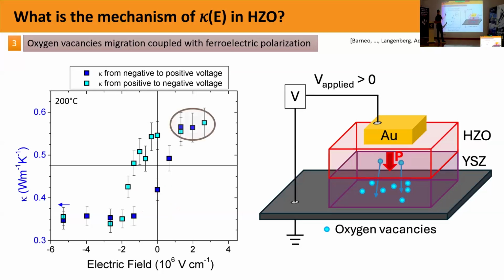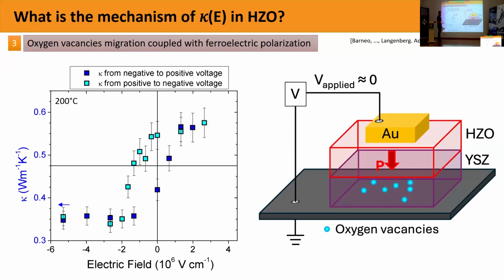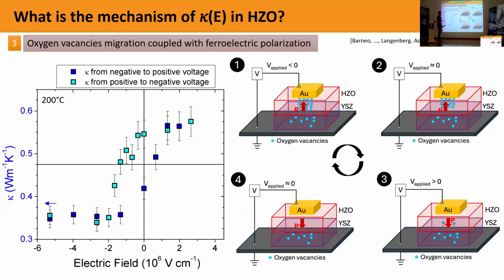Then we increase the voltage to the positive, sufficiently higher than the coercive field, so we switch the polarization as well. And then we push these vacancies to the YSZ again. And then the thermal conductivity is going to be high because we have removed our vacancies. And then, again, as before, when we go to 0, because of the polarization, the vacancies are not allowed to come back to the hafnium oxide. And that's why the thermal conductivity stays high. So we are finished, right?